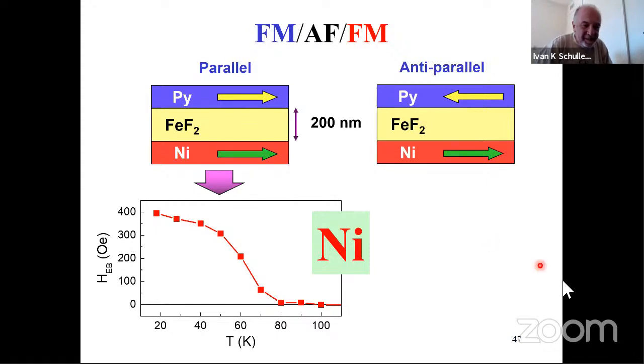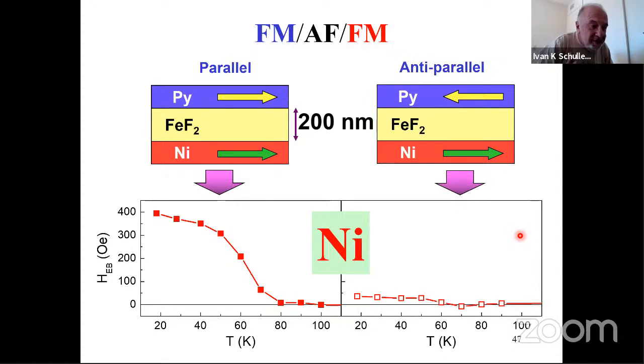something fantastic happens, something totally unexpected, as I've told you before. There is no exchange bias. The very same material knows that the permalloy layer, far away, 200 nanometers away, is reversed. What does this mean? It means that somehow some information is transmitted through the bulk. The bulk of the material plays a role. It's not only the interface.